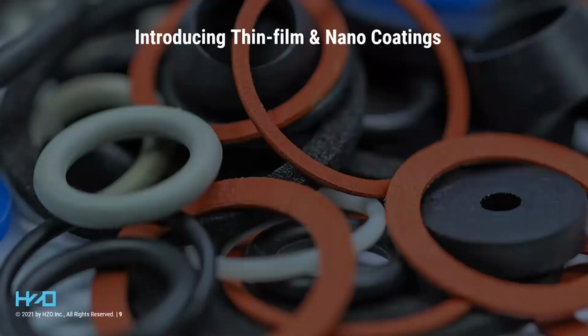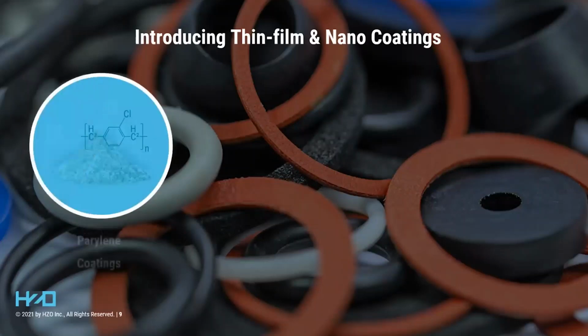So thin films and nano coatings are a broad grouping of materials, but they're generally applied under vacuum. Vacuum deposition gives us a number of strengths and challenges. Vacuum deposition is a batch process, as I mentioned before, and it's not suitable for all components, though in my experience, it works for most electronic components. Vacuum deposition does require more advanced masking than liquid coating, just because we're talking about molecules here that can get into a smaller space. Low pressure molecular flow in the vacuum means that it's much more conformal than liquid coatings. And building the coating molecule by molecule on the product means that you have a much more uniform coating as well. And I'll get into more of these in detail as we go along.